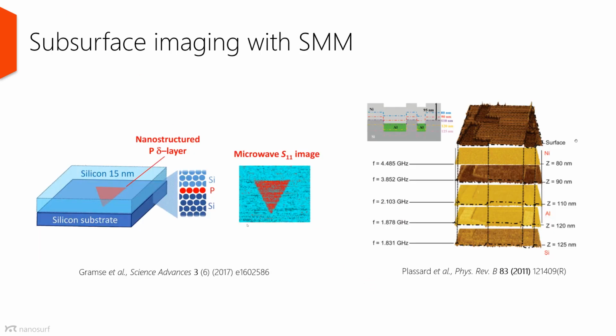And the subsurface imaging with the SMM is well documented. Here are just two examples of such imaging below the surface. One is the phosphorus layer buried below 15 nanometers of silicon surface, and it has a clear contrast in the S11 parameter. A second experiment is more interesting because there the researchers did sort of an SMM tomography by varying the wavelength. They were probing different depths below the surface, and they were able to obtain different images for different layers as far as 125 nanometers below the surface.